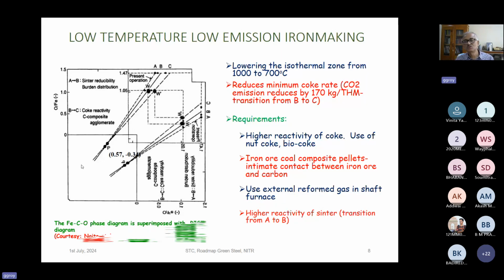But it is not a very easy task to reduce the isothermal zone temperature, because in the isothermal zone, the major reaction that takes place is the carbon gasification reaction, that is the in situ generation of CO. Since it is a highly endothermic reaction, it is very difficult to carry out the carbon gasification reaction to the full extent below 900 degrees centigrade. So that is the limit. But you can reduce the isothermal zone temperature and maintain the carbon gasification reaction if you can improve the reactivity of the coke. If the reactivity of the coke increases, then you can possibly carry out the carbon gasification reaction to its fullest extent, even below 900 degrees centigrade, by reducing the activation energy.